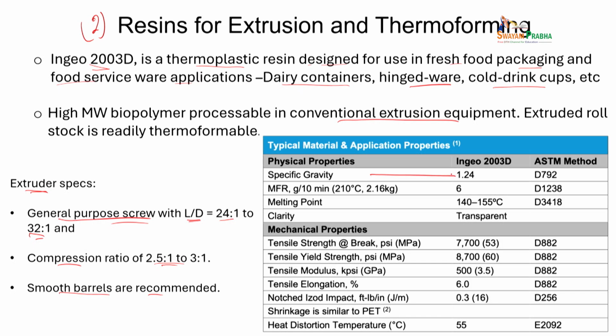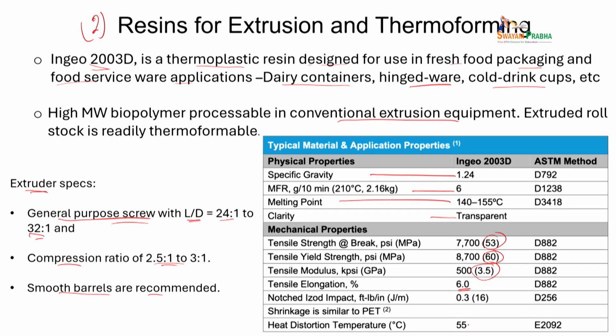Okay, and for this particular resin, you can see density is about 1.24, melt flow index is about 6, melting point temperature is given. It is mostly a transparent film or transparent container, and then you can see the properties: the tensile strength is about 53 megapascal, yield strength is about 60 megapascal, tensile modulus is about 3.5 gigapascal, elongation at break is about 6, that means it's not too flexible. LDPE can go up to 900 to 1000%, but this can only go 6%, and then there are impact and distortion temperature. So all these mechanical properties, thermal properties are also available to you.